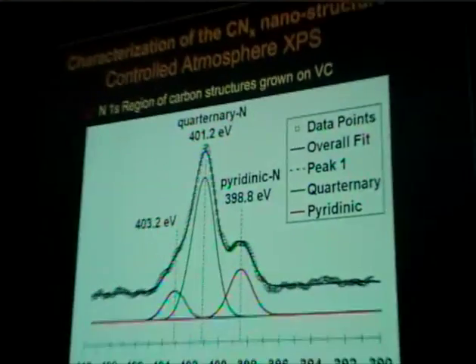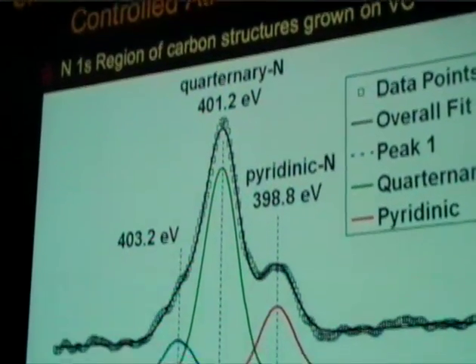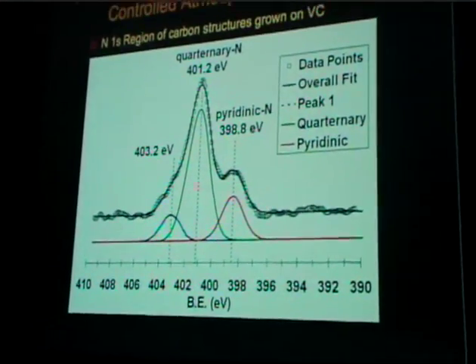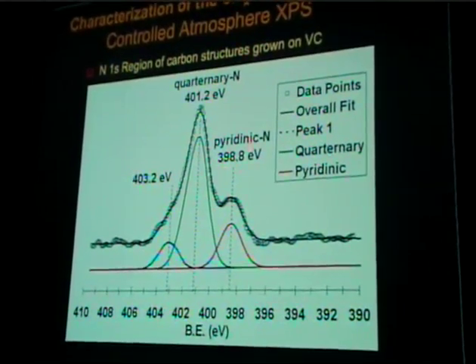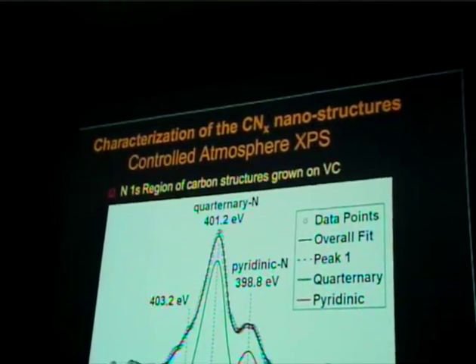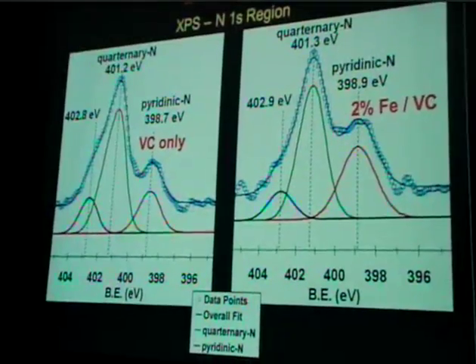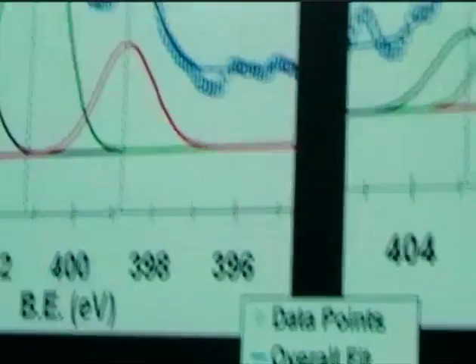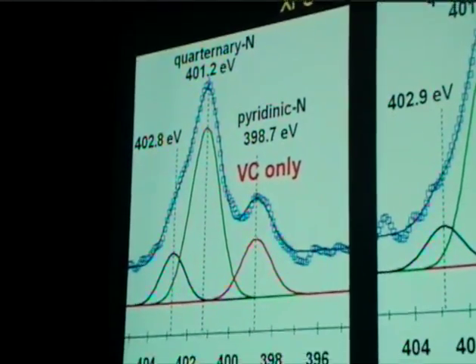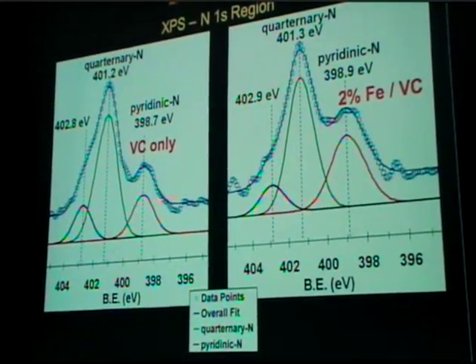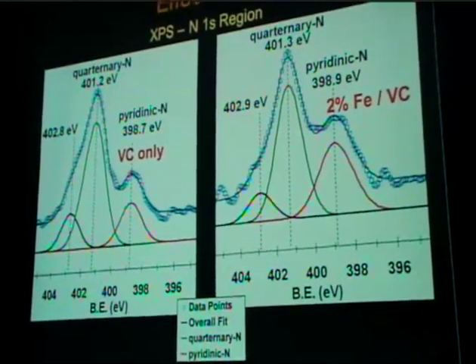And if we look at a typical sample, in this case, the nitrogen 1s region, carbon structures grown on Vulcan carbon, we are able to differentiate the quaternary nitrogen and pyridinic nitrogen. This one, at this point, we're suspecting that it may be an oxidized form of the pyridinic nitrogen. And again, if we compare the two materials which are grown on Vulcan carbon only versus iron-containing Vulcan carbon, there's a definite increase in the pyridinic nitrogen content, which is very easy to see. And this is the catalyst that gave us the higher oxygen reduction reaction activity.